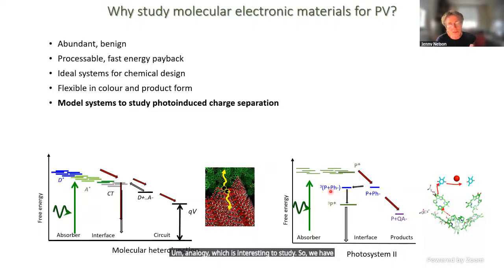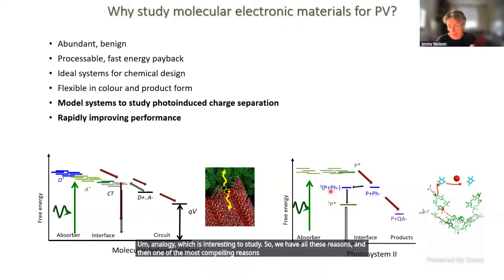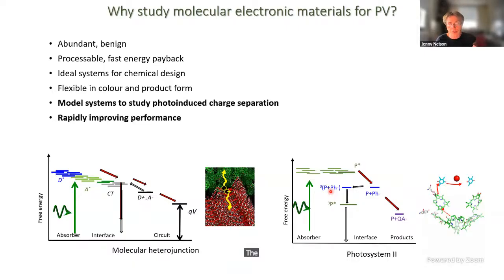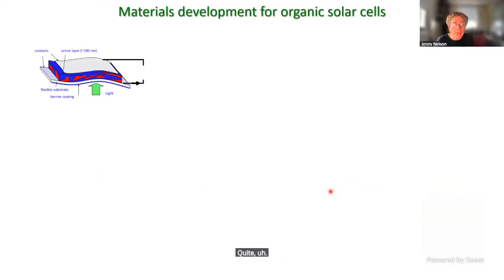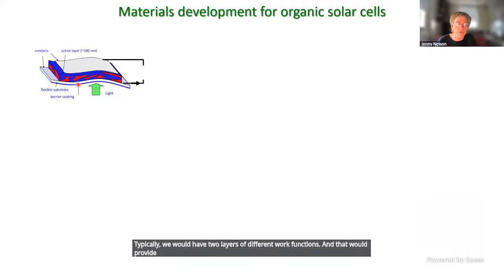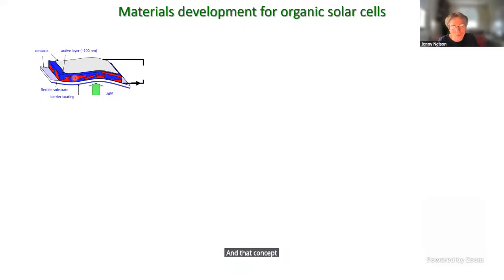So we have all these reasons, and then one of the most compelling reasons is actually that recently the performance of solar cells made from molecular materials has been increasing quite rapidly. So this is a typical device structure where we have two electrodes. They need to be electronically different in order to drive a photocurrent. Typically, we would have two layers of different work functions, and that would provide a direction for photocurrent to be generated. And in between, we have our semiconductor active layer that contains a mixture of two different organic semiconductors. And that concept hasn't really changed over the last 20 years.